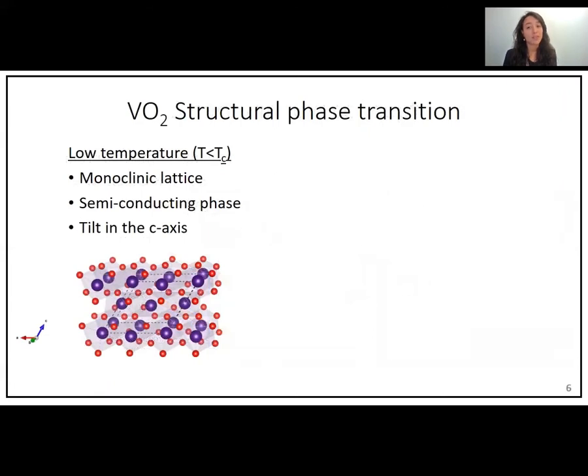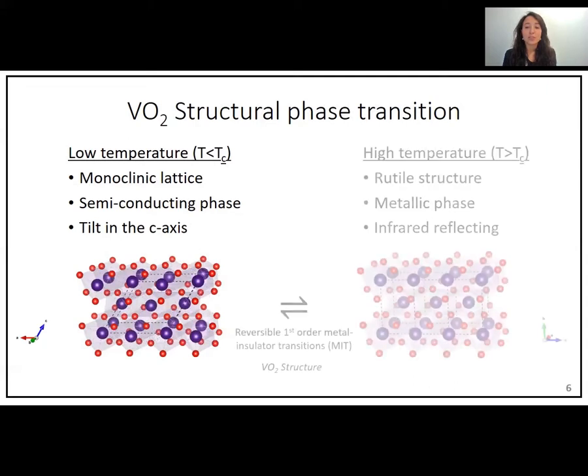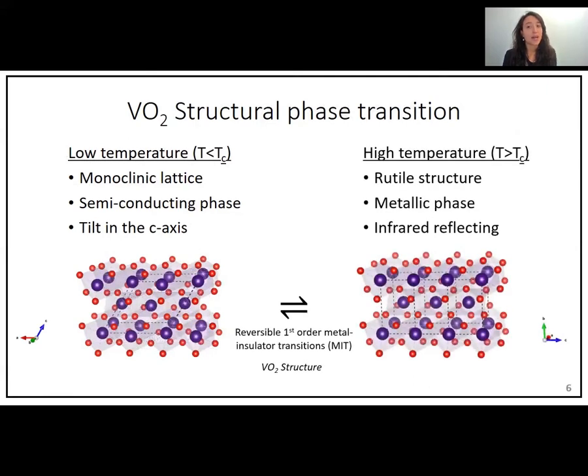More specifically, the vanadium dioxide structure has 6 polymorphs. The most important is the monoclinic vanadium dioxide, as this is the structure that changes to tetragonal when heated. The structural phase transition is reversible and is referred to as the metal-to-insulator transition. Due to the tilt in the c-axis, the material changes from being semiconductive to metallic, which means it becomes infrared light reflecting.